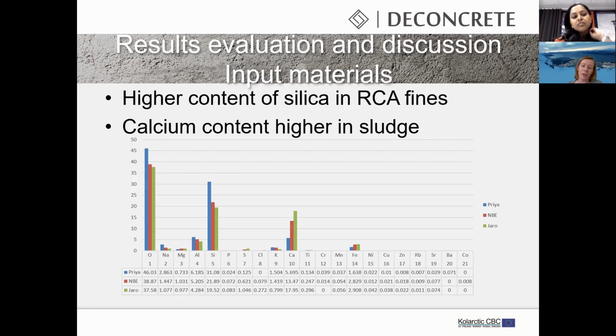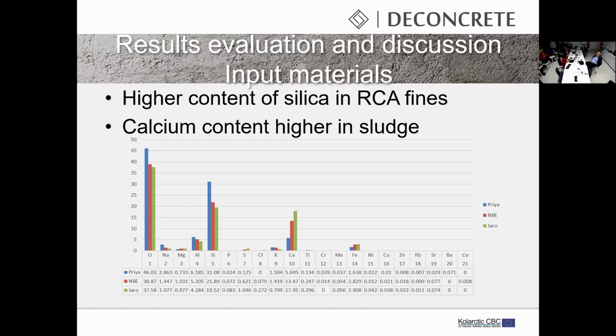We can see there was a higher content of silica in the fines from crushing of concrete than in the sludges from concrete production, while there was a higher content of calcium in the sludges due to more leftover cement paste, especially in the case of Jaro, where the sludge includes washing of the concrete trucks.